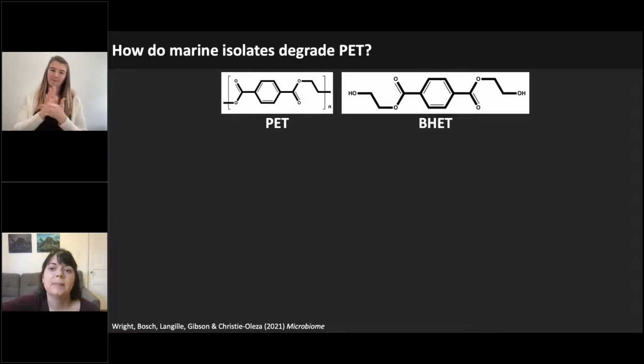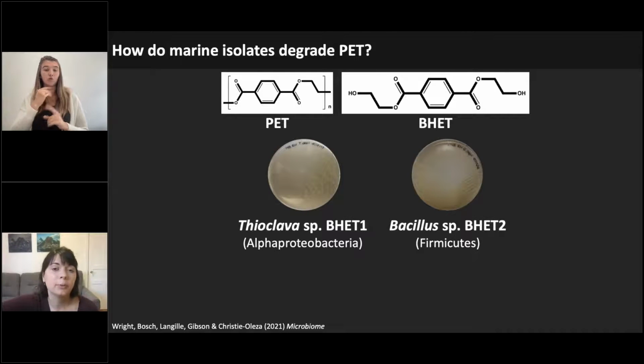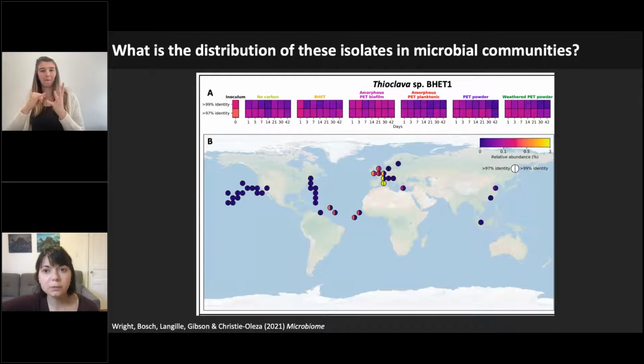So from the isolations that I mentioned previously that used PET and BHET, we managed to get 2 bacterial isolates that seem to be able to grow with these substrates as the only sources of carbon, which we identified as Thioclava and Bacillus species. And first of all, we just had a quick look at whether DNA sequences matching these isolates were present in our communities. So that's the ones that we incubated over 6 weeks, shown at the top.